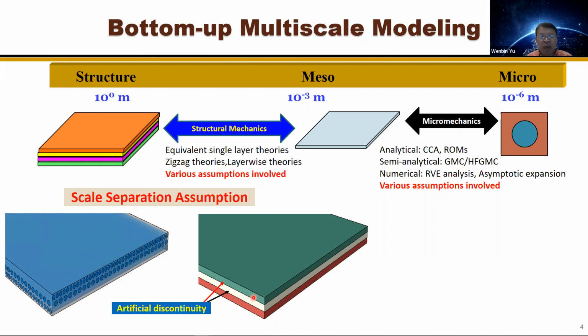We have about 20 fibers with the layer thickness. Then for the global behavior, stiffness and vibration modes and buckling, that would be okay. But it would not be okay to get the stress concentration because even the material discontinuity is different. And that's why, for structure behavior, for stiffness consideration, the classical lamination theory does a good job there.